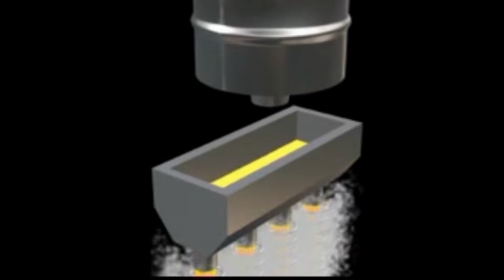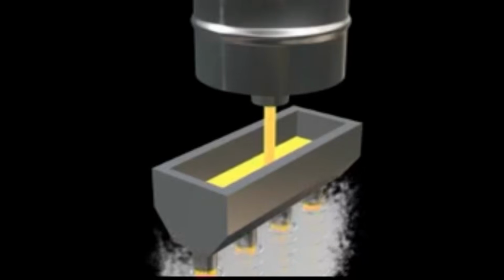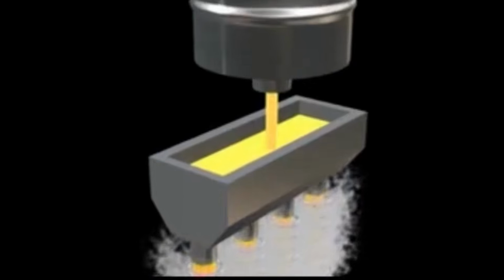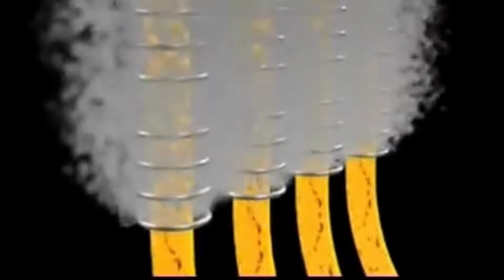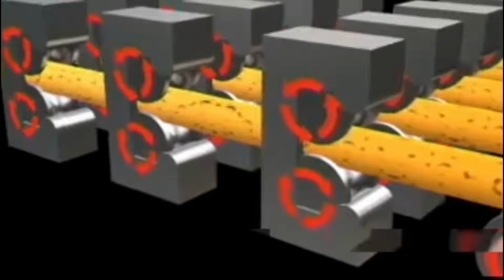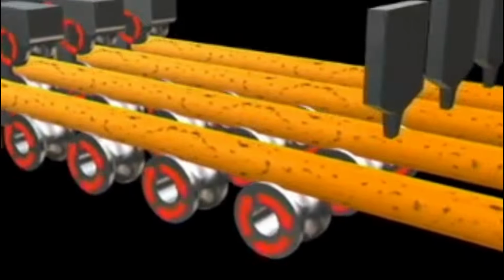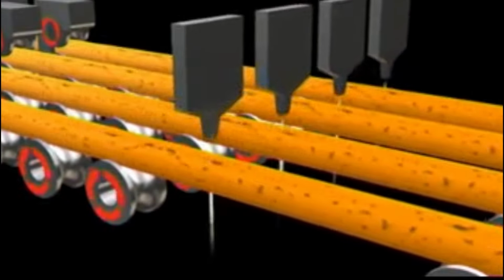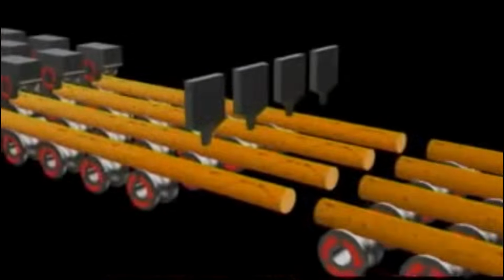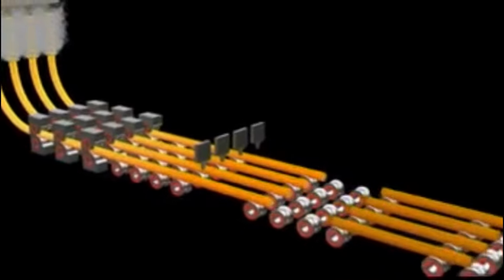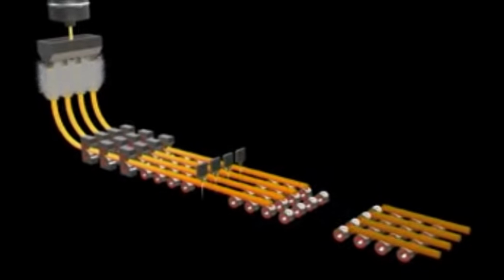The molten steel is delivered to the continuous casting machine, where the ladle pours its charge into a tundish that distributes the flow uniformly into the molds. These molds solidify the steel into round solid billets with diameters ranging from 148 mm to 310 mm, and annual production exceeds 1,200,000 tons of billets.